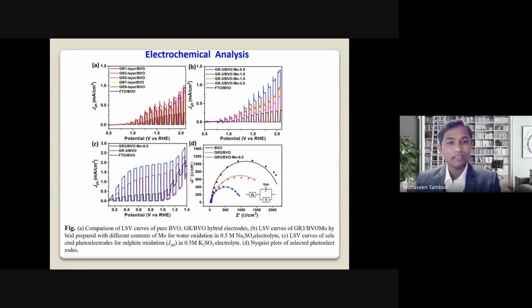In that case, you can check here that 0.5% molybdenum-doped graphene BiVO4 shows the highest photocurrent, meaning the higher the photocurrent, the more hydrogen we can produce. Figure C shows the sulfite oxidation we did. Actually, we studied both sulfide oxidation and sulfate oxidation.